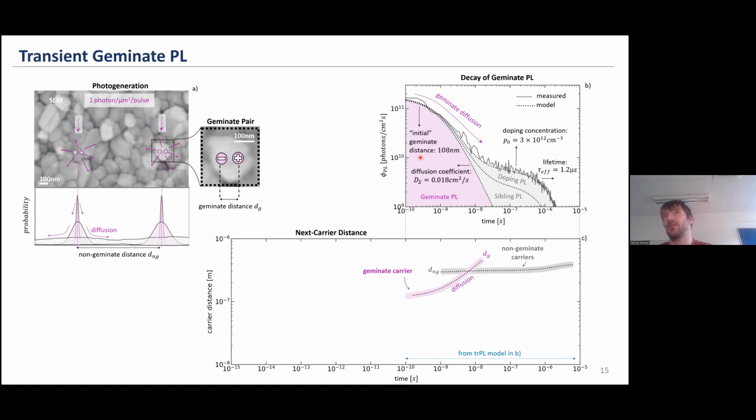And then I asked myself, okay, what is actually this initial geminate distance between the geminate carriers? And I had a little look through the literature, and I found a nice work of Zhang. And I converted their data to this distance to the geminate partner. And it fits actually very nicely to my data. And what they measure from transient absorption, they have at the femtosecond time scale, they measure the hot carrier transport. They measure how far the carriers transport or how far the carriers separate during the time they need to cool down, and this is by ballistic transport.